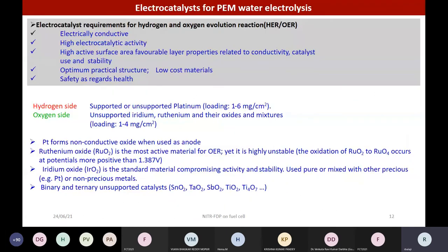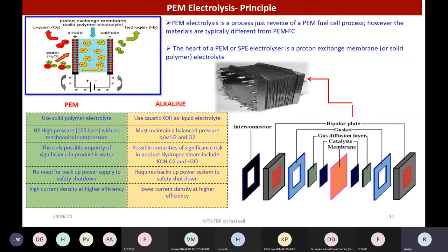One of the reasons for increasing the cost of the PEM based technology is that, unlike fuel cell, where we can use any graphite carbon based material for the cell construction, though electrolysis is the reverse of the fuel cell, you cannot use any carbon-based material for the cell construction. Because, as I said, the voltage requirement to split the water molecule, practically, is about 1.6 to 2 volt. Whereas in the case of fuel cell, the operating voltage will not go more than 0.6 to 1 volt actually.